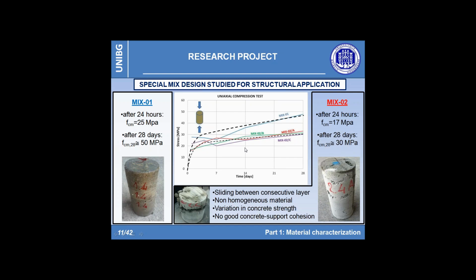After assessing the reliability of different cementitious materials in terms of stability and absence of sliding phenomenon, uniaxial compressive tests on several cores extracted from the structural wall have been carried out and a maturation curve has been defined. Two different types of cementitious material have been tested during the preliminary test. The first one, named Mix 1, has appeared to be homogeneous in terms of mass density and reliable in terms of structural response, reaching a mean compressive strength after 28 days curing equal to 50 megapascal, and especially showing an average strength at 24 hours equal to 25 megapascal,